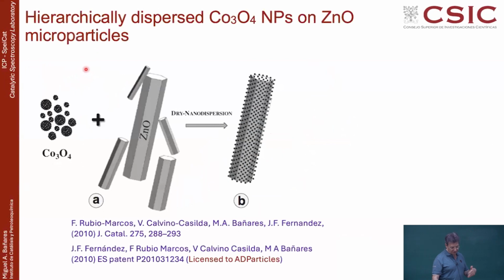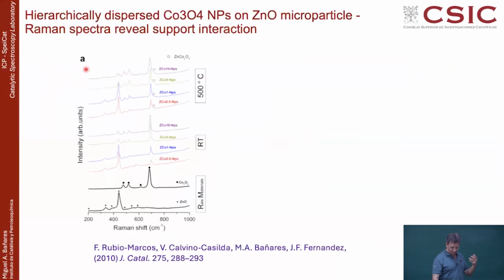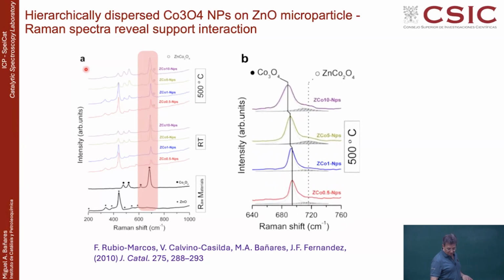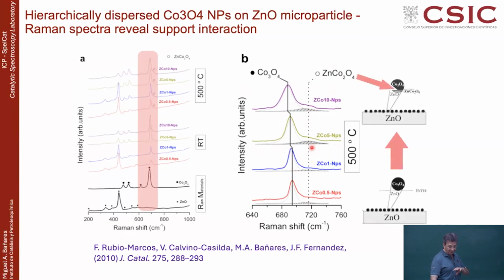So we have a catalyst, which is cobalt oxide on zinc oxide, which works nicely. Here you have some Raman spectra. Basically, it's a catalyst with cobalt oxide and zinc oxide. So the Raman spectra show you Raman bands of cobalt oxide and Raman bands of zinc oxide. And interestingly, it is just made by nanomechanically mixing these 2 powders. If you increase the temperature, you get some additional phase from the reaction between cobalt and zinc, which is the spinel, this phase over here. But otherwise, you will have the cobalt, which is distorted by interaction with the zinc, but still cobalt. Now, the nice thing is that this cobalt, which is affected by zinc but remains like cobalt, is the active phase. And when you get the spinel, the system is not working. So it's an incipient interaction between the cobalt and the zinc.